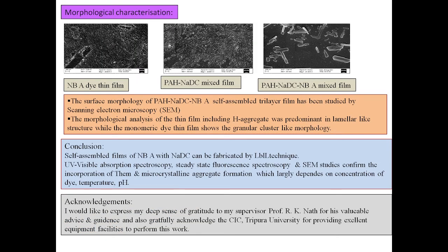Now the morphological characterization of the film has been studied. The surface morphology of the PAH NaDC NB self-assembled trilayer film has been studied by scanning electron microscopy, or SEM. The morphological analysis of the thin film shows that H aggregate was predominant in a lamellar-like or thin plate-like structure, while the monomeric dye thin film shows a granular cluster-like morphology.